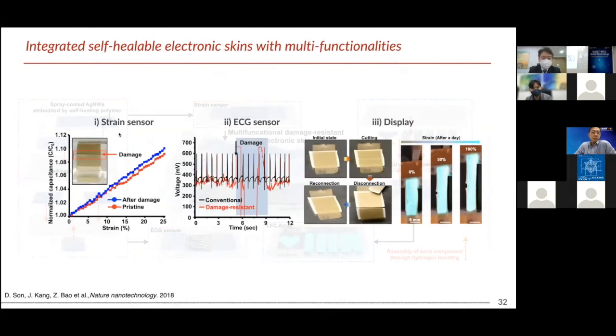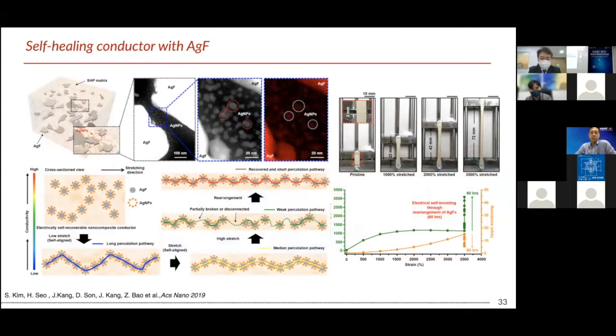They are composed of the strain sensor, the ECG sensor and the display. So all of the components are a fully self-healable system. So even after damage, they can restore the sensing ability and also their light emitting properties. And also this approach is not limited to 1D nano networks, so it can also apply to 2D systems. So even with silver flake systems, they can show very dynamic behavior. We found a very interesting electrical self-boosting event inside of the polymer matrix.